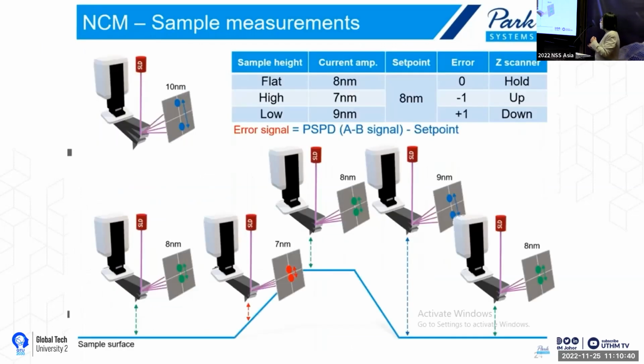So in the non-contact mode, when you're doing the test, you have to set a set point. It depends on the skill of the operator whether you can get the right set point or not. If not, then you don't get good imaging. When the set point is set, your cantilever will scan over, let's say, a step height sample, and you maintain the set point, say 8 nanometers. Any difference between the detected position and the set point is the error signal, and that error signal gives you the topography on a single line scan.